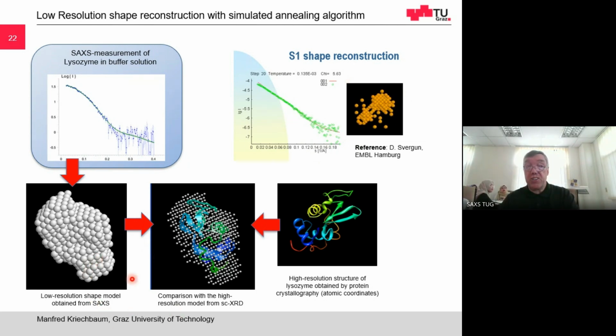So once you have found your model, you compare it with the data which were obtained by another technique like crystallography or NMR. So many proteins were crystallized, and the structure was solved with atomic resolution. They deposit it in a data bank or database, and there you can retrieve this data and compare it with your shape, with your low resolution SAXS data. Like in that case, this is lysozyme. So you overlay both results, and then you can say if it fits or if it is plausible with the model or not.